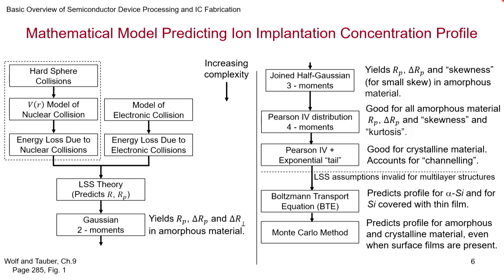Okay. So, this is what is interesting about using parameters which are of course physical. You know that there is a 4th moment that you are trying to calculate. So, this is good, but sometimes there are some special situations, especially when you are implanting, you are not sure that you are necessarily implanting in an amorphous material. You may be implanting in a crystalline material. Crystalline materials will behave a little differently. You can have some channels formed. If it gets into a channel, it may keep going through the crystal lattice without being stopped so effectively. So, it ends up going a little deeper.